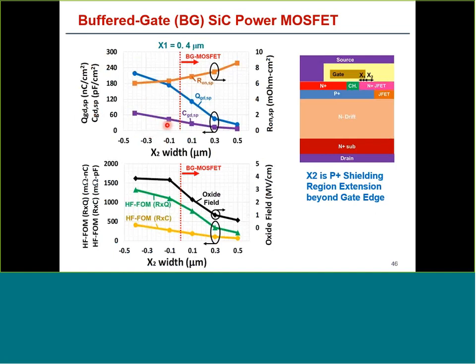In terms of capacitance and QGD, you can see a rather complex plot here which shows what happens when we fix X1, which is this dimension, at 0.4 based upon alignment tolerances and the FAB, and then we look at what happens with X2 being changed. Now, we have defined X2 as the amount of extension of the P+ region beyond the edge of the gate. So positive values of X2 show this extension, and that is representative of the BG MOSFET. When X2 becomes negative, the gate is now extending into the JFET region, and that is actually like the cut gate device or split gate devices over here.